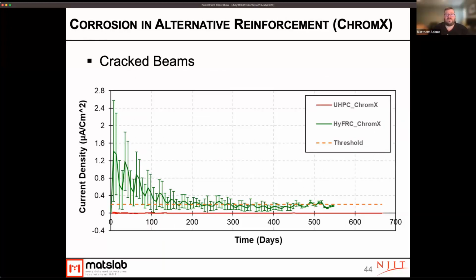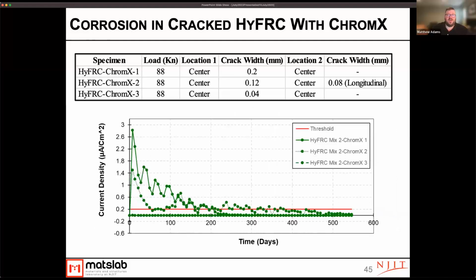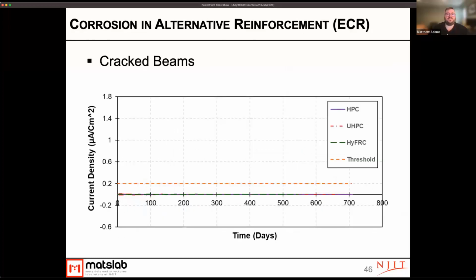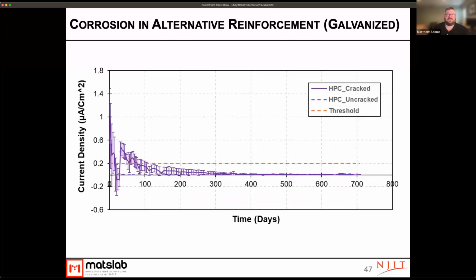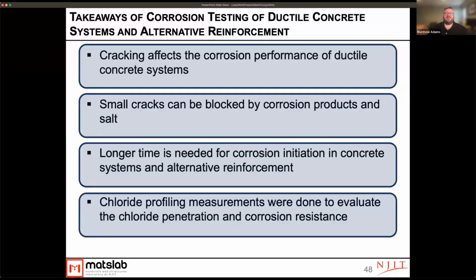Our alternative reinforcements, we see that, again, the HyFRC, even with the Chromex, had a corrosion density above the limit there. So likely even that Chromex was starting to corrode. Again, that was a system with a fairly large crack. But in our other cracked beams with alternative reinforcement, we still weren't seeing any corrosion. Our galvanized systems with the HPC, again, no corrosion happening there. And so in general, all of these systems performed well in corrosion.